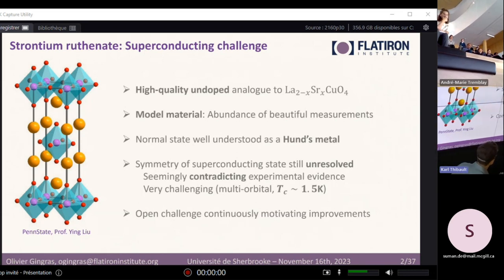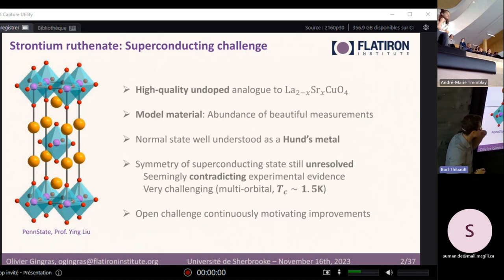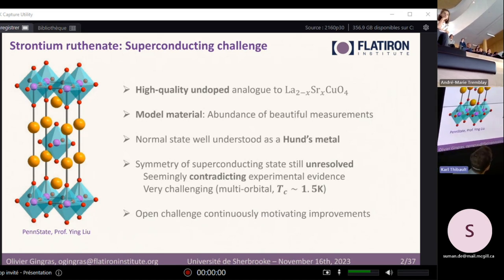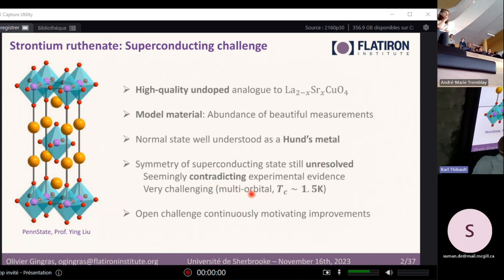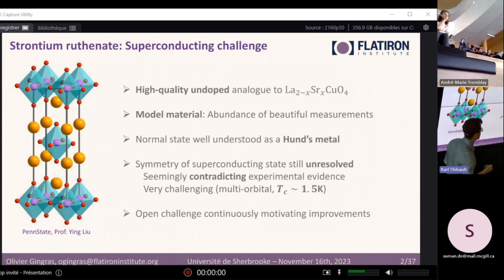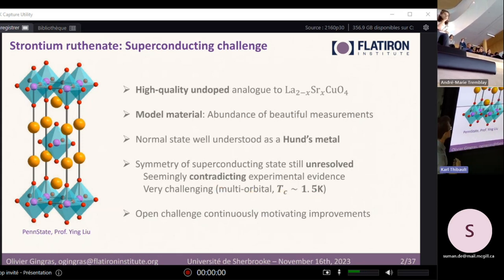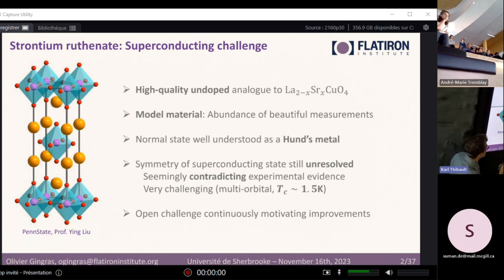There are experiments that, if you interpret them in a specific way, give different conclusions on the nature of the superconducting state. And it's not surprising. This is a very challenging system with many orbitals involved, spin-orbit coupling, and the critical temperature at which we find it to be superconducting is very low. But still, this material being a model in the normal state, if we have a good theory of superconductivity, we should be able to also predict this superconducting state.